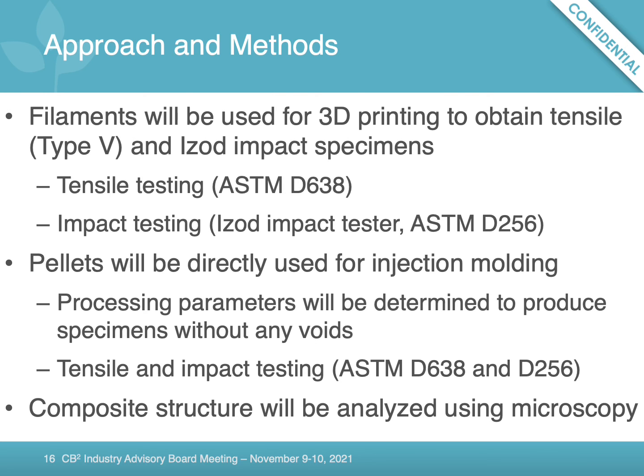The pellets will be directly used for injection molding, as I mentioned before, and we will definitely determine the ideal processing parameters to produce specimens without any voids, and we'll produce tensile and impact testing specimens and test them according to the ASTM standards here. We'll also produce flexure specimens and test them as well. And the composite structure will be analyzed using microscopy.